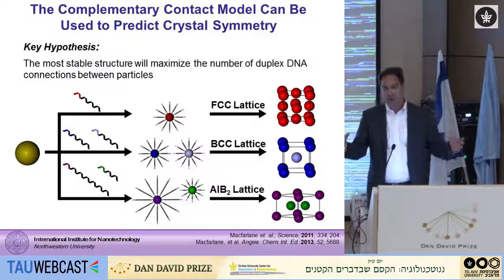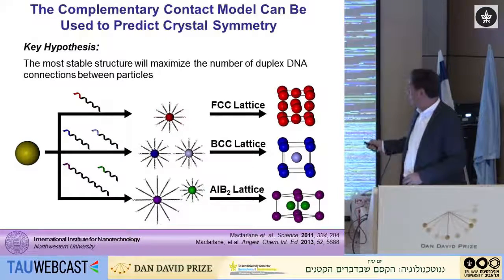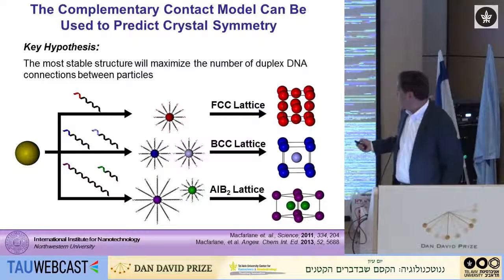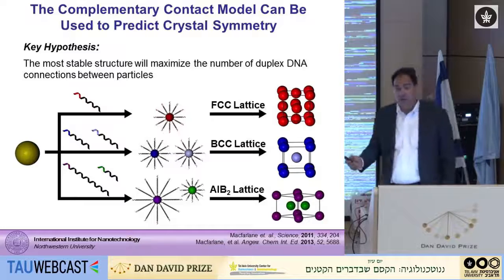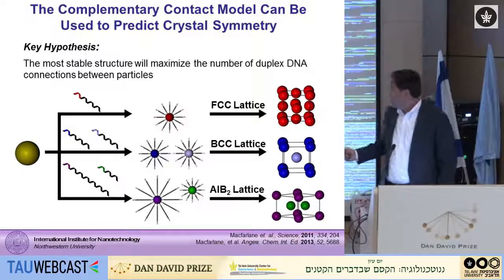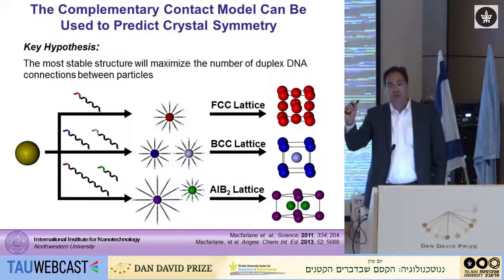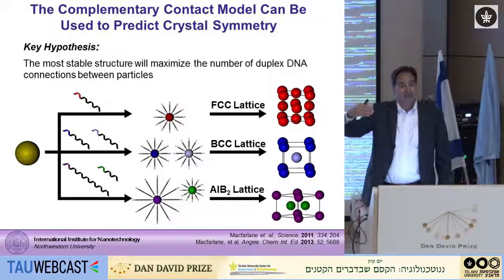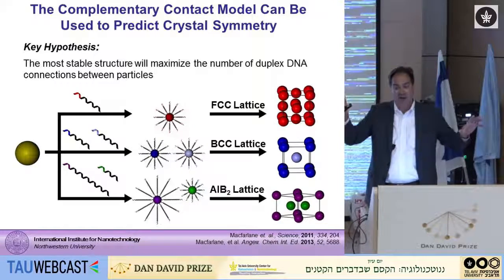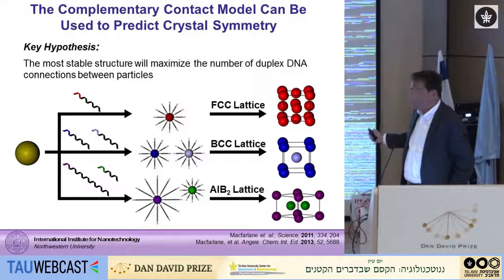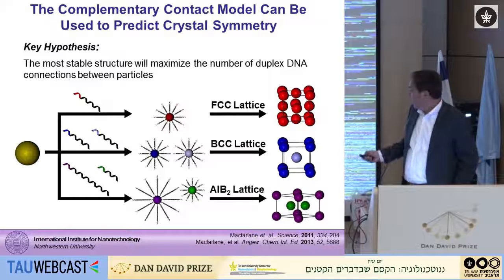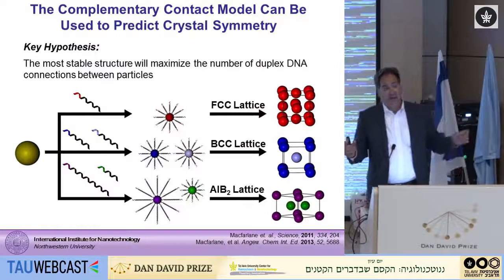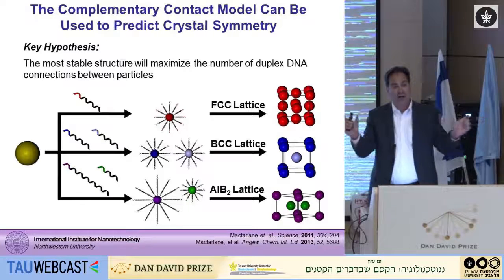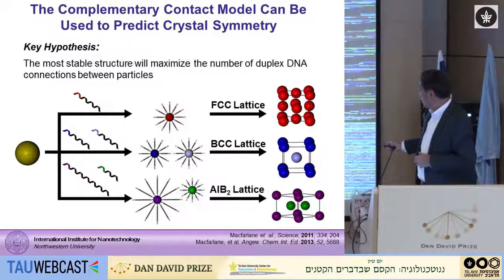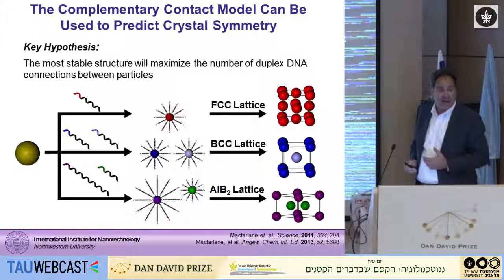And so now you can begin to play games. And you can say, well, if that's true, I can test that. Because if I wanted to form an FCC lattice, I'd have to create a structure where every particle could interact with neighboring particles, 12 nearest neighbors. And I can do that by creating a particle that's self-complementary to itself. So if I terminate that with GCGC, if I flip that around, that's CGCG. So all those particles can interact with one another, and in principle, if this is correct, should fall into the FCC structure. If I want a BCC structure, I don't want self-complementary particles. I want two particles that recognize one another and come together. And that's a structure that has eight nearest neighbors. That's the most efficient way of packing these types of architectures.